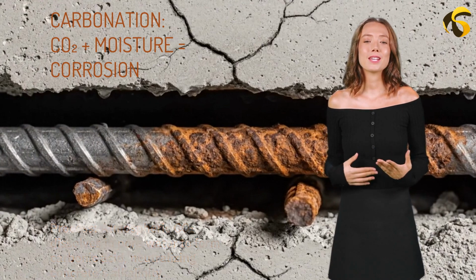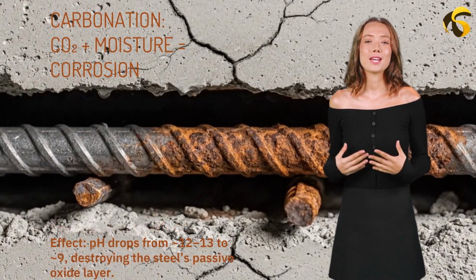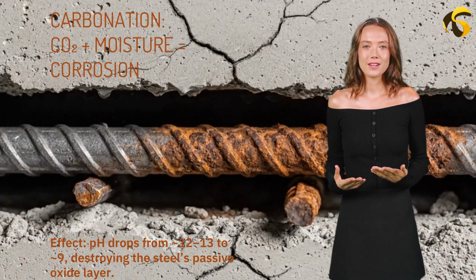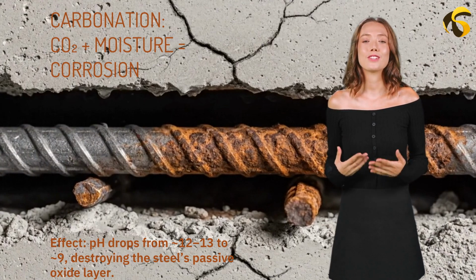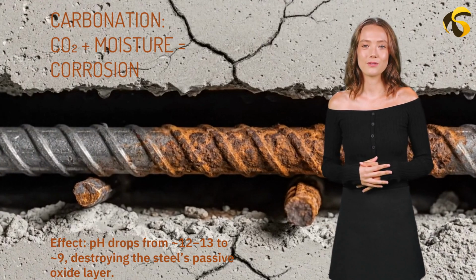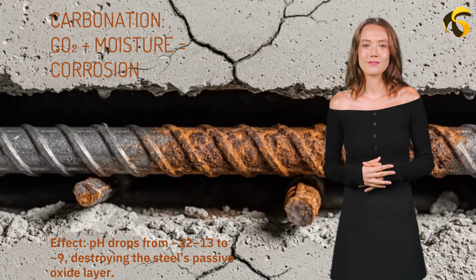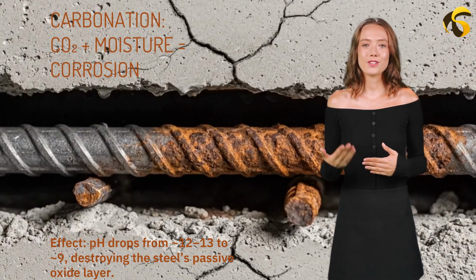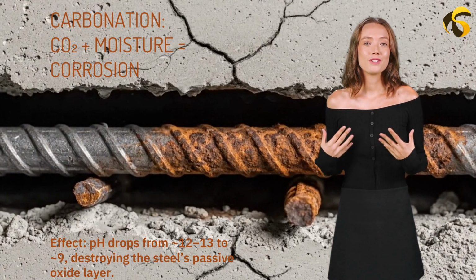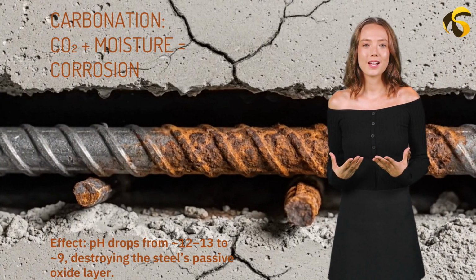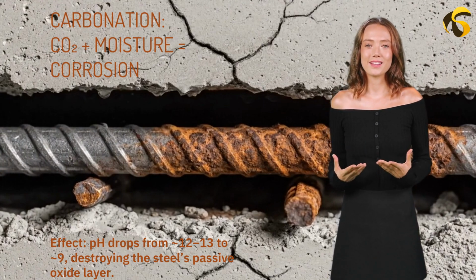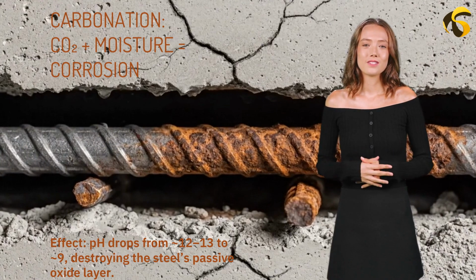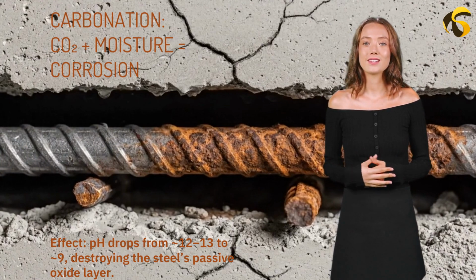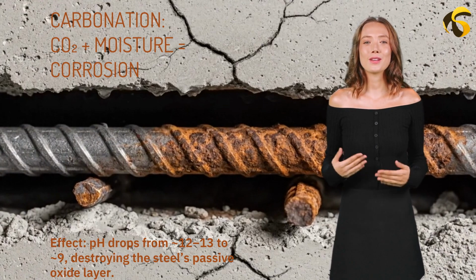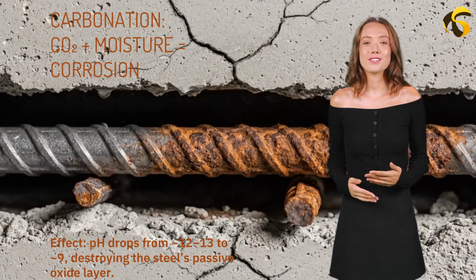Rust, iron oxide, occupies up to 6 times the volume of the original steel, so as it forms, it pushes against the concrete, causing cracking and surface spalling. You've probably seen concrete where chunks have popped off, exposing rusted rebar. That's likely carbonation at work. It begins as soon as concrete is exposed to air and typically advances 1 to 5 millimeters per year, depending on how porous the concrete is.